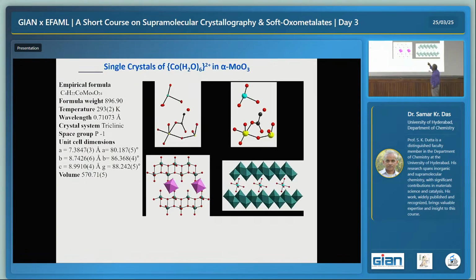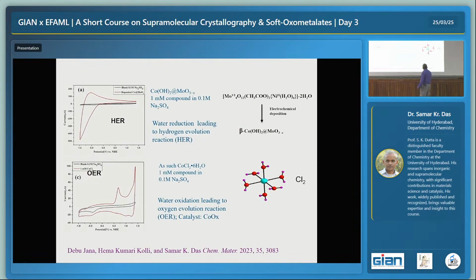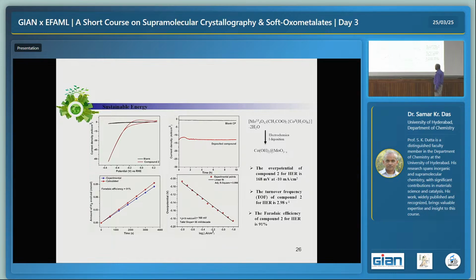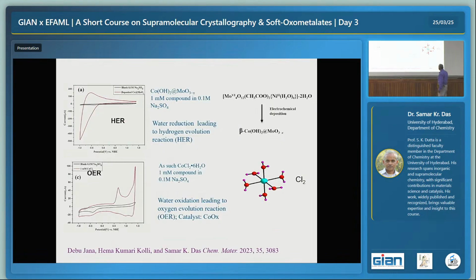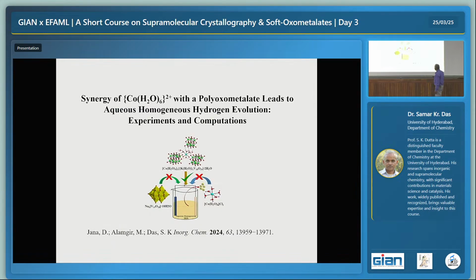So this single crystal of the parent compound, again it is a triclinic system like nickel 1, and in this case also the asymmetric unit I am showing here in the thermal plot, and this is the other integration compound. So I again tell you, very surprising that cobalt chloride, if you take from the bottle, it will give water oxidation, OER, but in your case when it is in the layer, it becomes molybdenum bronze, it gives hydrogen, HER. And these are the parameters.